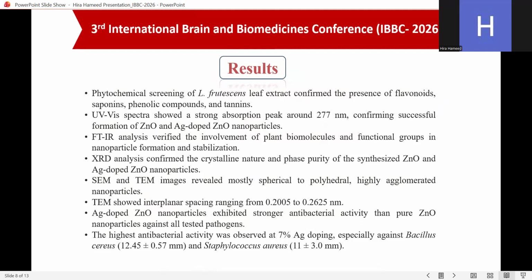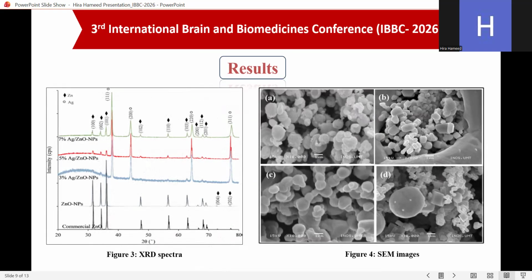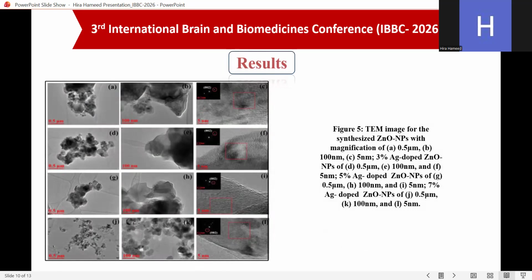The highest antimicrobial activity was observed at 7%, the highest percentage of silver doping, especially against Bacillus cereus and Staphylococcus aureus. It means silver doped zinc oxide nanoparticles have more sensitivity against gram positive bacteria as compared to gram negative bacteria. As I showed before, here are TEM images of the synthesized zinc oxide nanoparticles with magnification of 0.5 micrometer, then 100 nanometer, at different concentrations, different percentages.